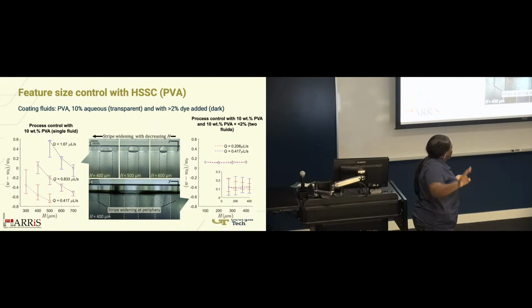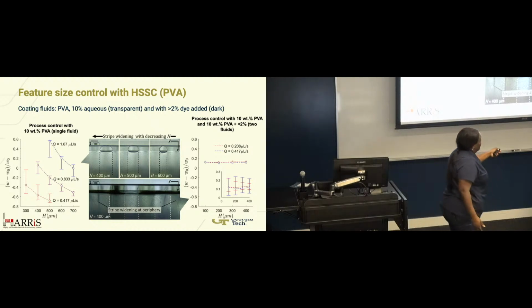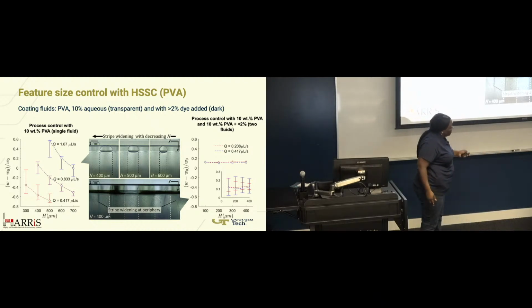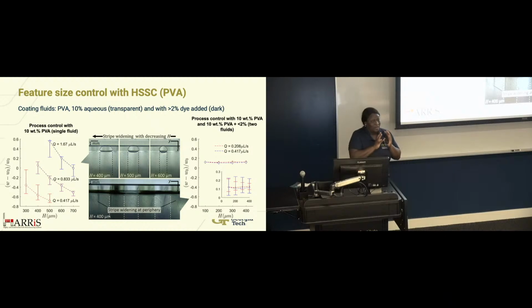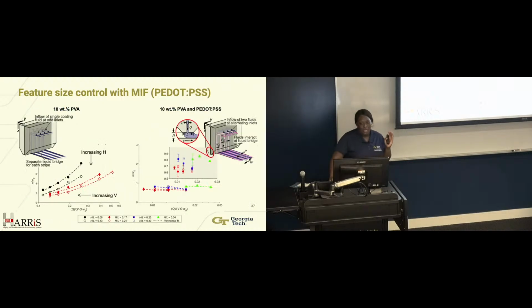But whenever we go to two or more materials, look at what happens. It's like no impact. So we can process more stably. And so we're looking at two different flow rates. So the flow rate is negligible in this particular case in terms of the change in width and H. And so we believe this is due to some scaffolding effects that we get. And so all of a sudden, we can process materials without having to tune them or alter them. We can process them in their real states.